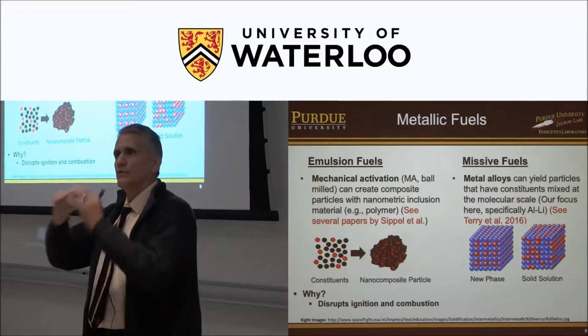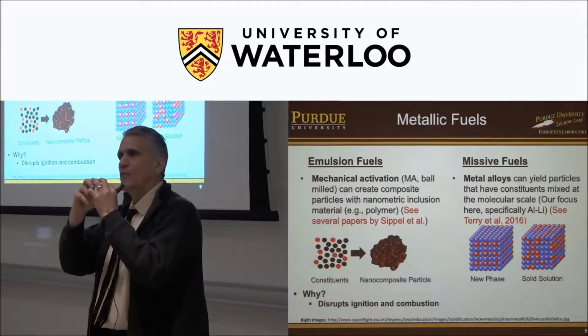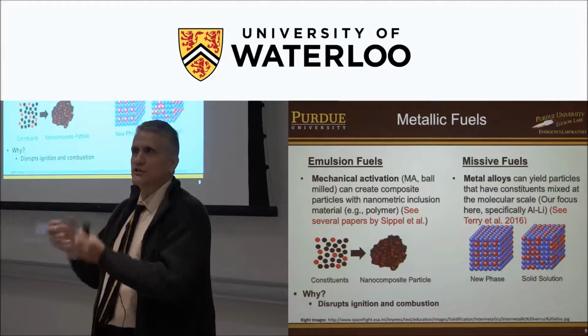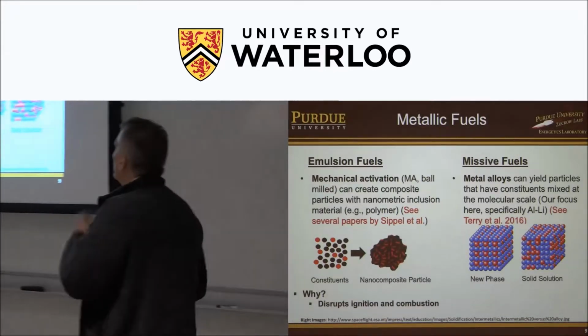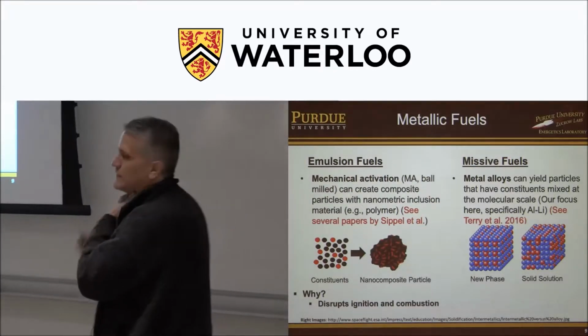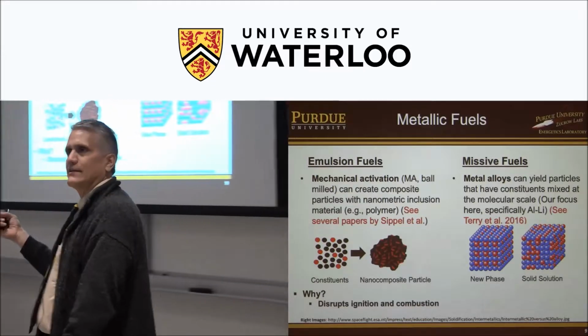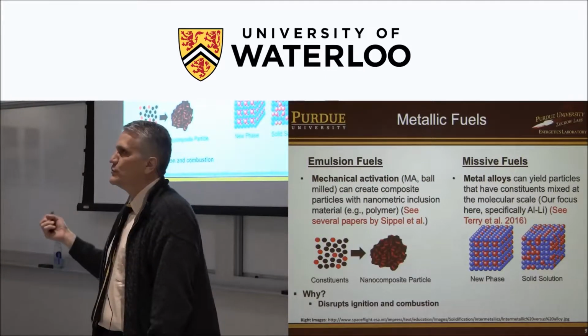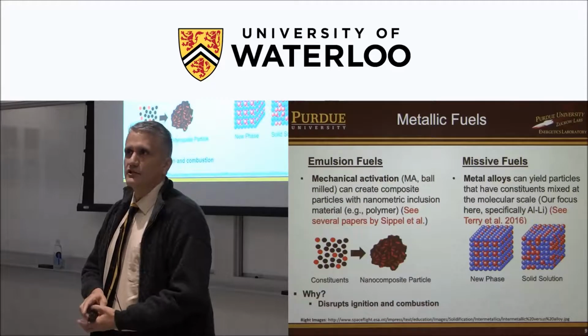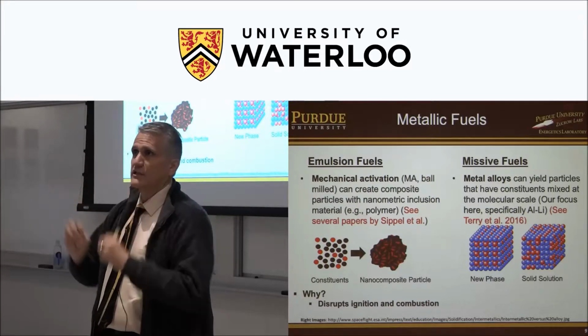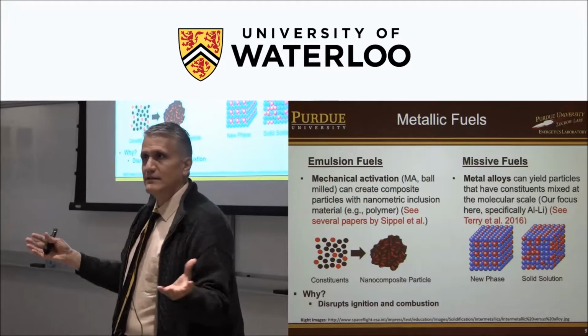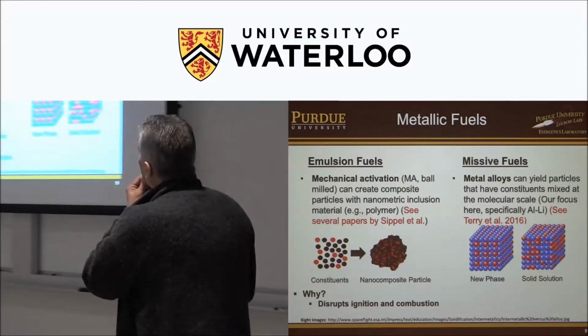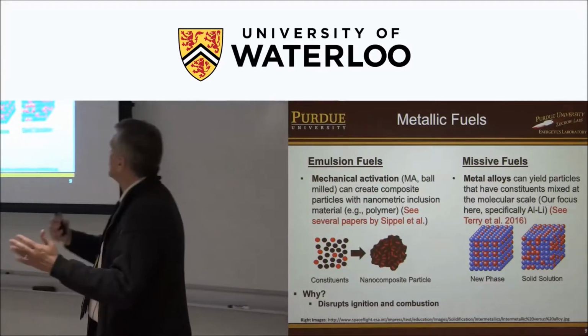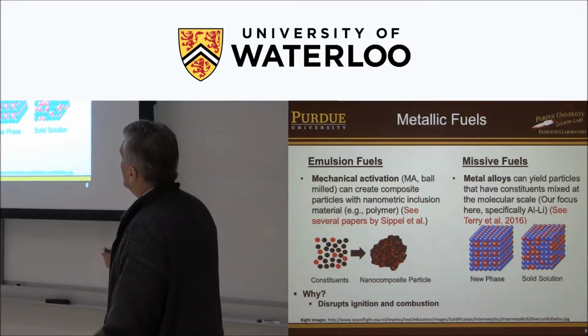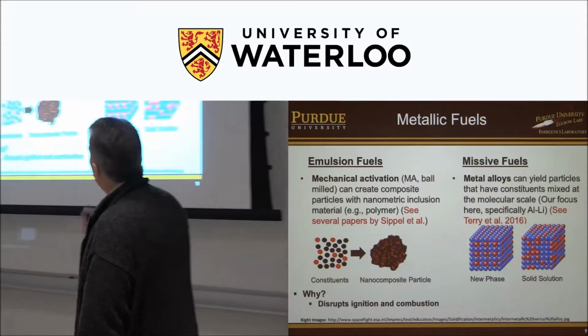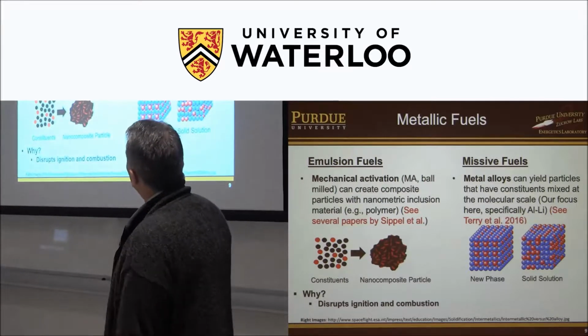So it could be a fuel oil with tiny droplets of water inside. When that's heated in the combustion system, it could shatter and micro-explode those liquids. Likewise, if you have emissive fuels where the volatility, the boiling point of the constituents, are very different, you can have conditions such that the droplets will micro-explode, sort of self-atomize, and form smaller droplets that could burn faster, more complete combustion, etc. So on metals, an analogy to the emulsion fuels is what we call mechanical activation.